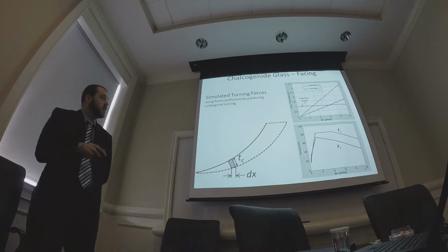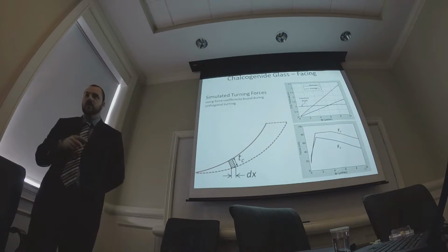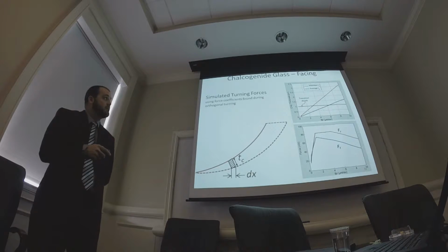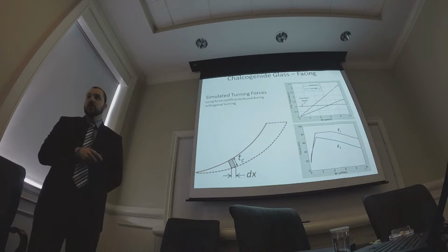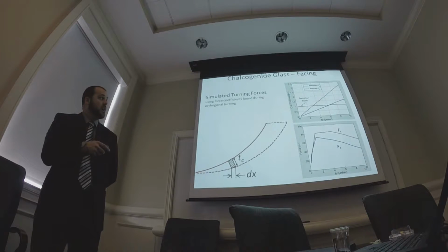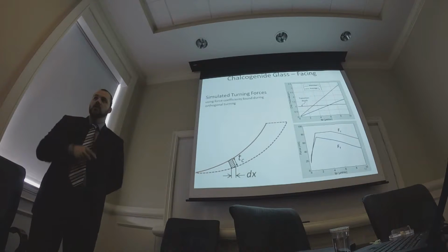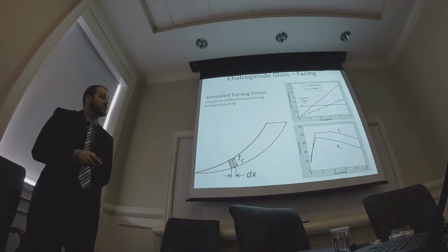So here I'm sort of mapping this transition depth that we think we're going to switch between ductile and brittle, and the maximum chip thickness along the chip and the average chip thickness. So from this we expected somewhere around the 5 micron feed per rev that some brittle fracture would be occurring. But at 2, everything should be below that transition depth. So this is the predicted forces here.